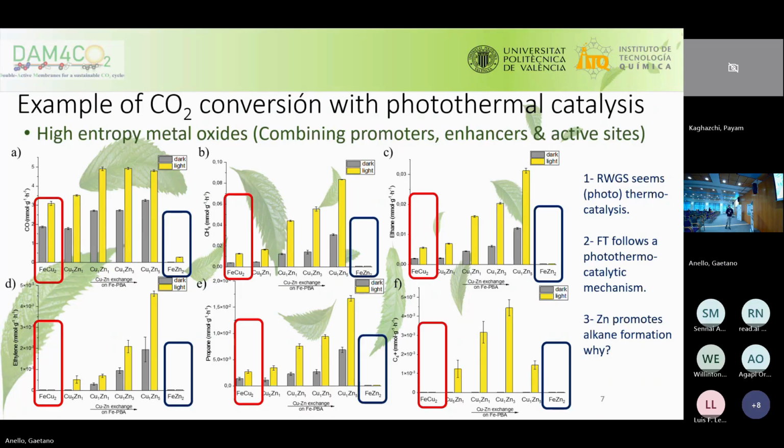And just to point it out, when you have a synergistic effect, you may have an increase of, I don't know, multiplying the production by 5 or by 6. So the most effective one, in our case, is when we have 5 times of zinc per 1 of copper.